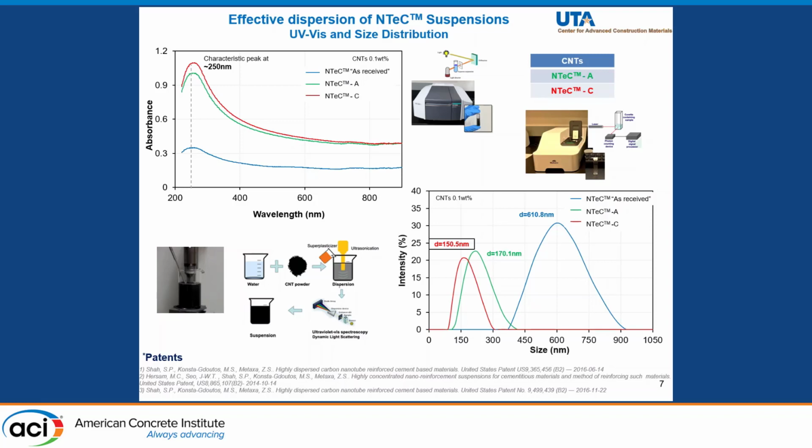During ultrasonication and at the end of the sonication procedure, we can see that the absorbance around 250 increased to higher values, and this is the result of the ultrasonication procedure that disentangles the individual CNTs inside our suspension.